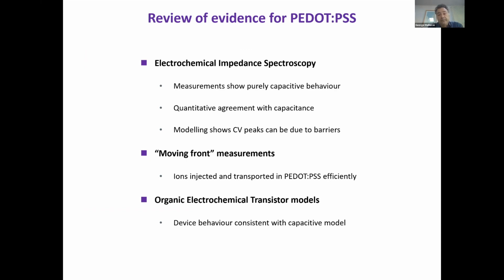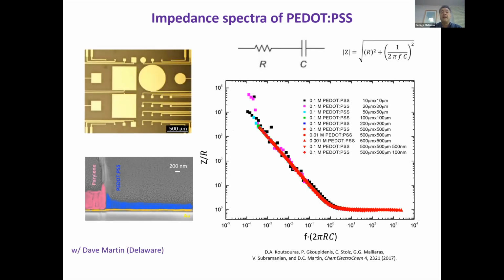So let me review the evidence. From electrochemical impedance spectroscopy, we've seen that it behaves in an ideal fashion. From so-called moving front measurements, we can look at the motion of ions in this film and show that there is an electric field inside the film during electrochemical doping processes. And then from device work, we can understand fairly sophisticated device behaviors by a very simple capacitive model. So let me go through the data really quickly.